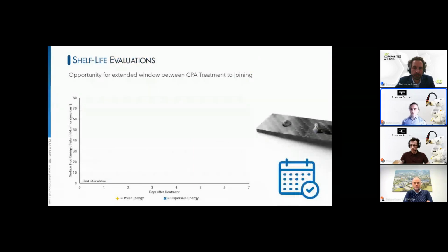Another customer came to us looking to understand how long between treatment and the time that they can bond, how long could they leave it. We had previously observed that 22 days was viable on other material types, and so we do prefer to do these kinds of tests specifically with customers for their specific surface, because every time we do a CPA treatment, it creates a new interface. So when we evaluated the surface-free energy of our CPA prepared material for them over the course of 7 days, it was observed to remain above the threshold requirement for the customer's preferred adhesive.